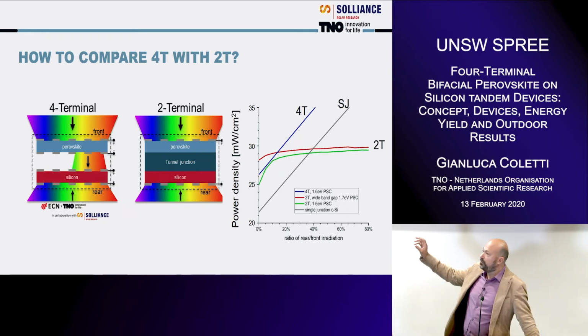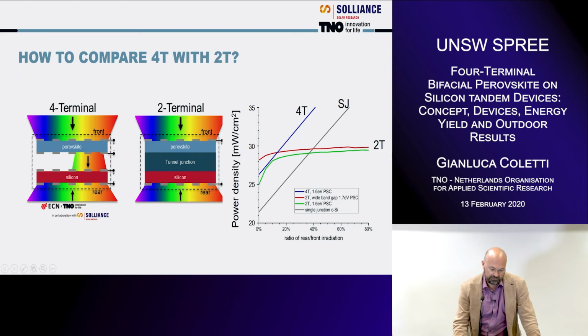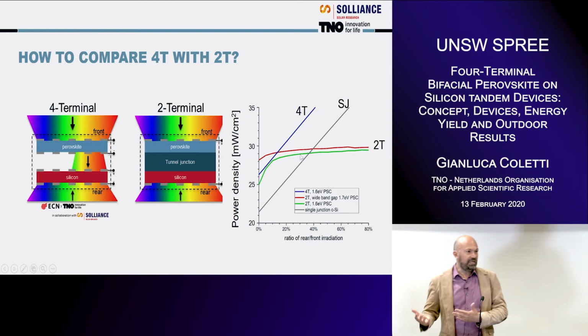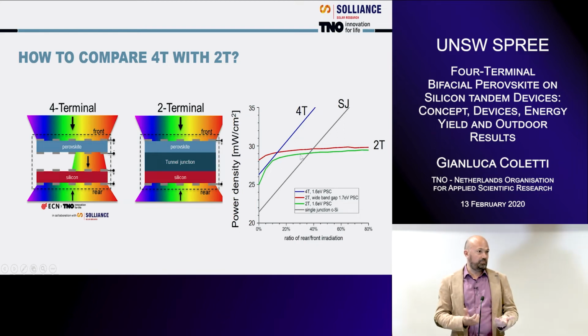My colleagues started to design, first of all, a single junction device. That's what you see here. You add a certain ratio of the light from the rear side. This is 20%, and you see that it's nicely linear. Why? Because it's just a single junction device. When you use the 4-terminal device, the linearity is kept. But of course, you get a higher power density as a function of the rear irradiance. And what you expect on the 2-terminal device is that at a certain moment, the power density is capped. Why? Because of the limitation of the current generated in the top device.